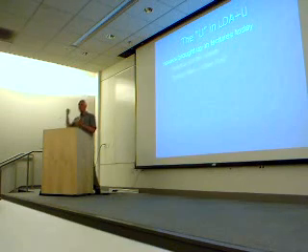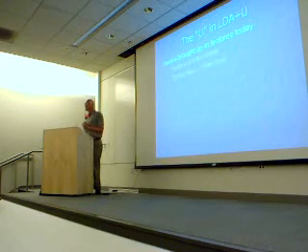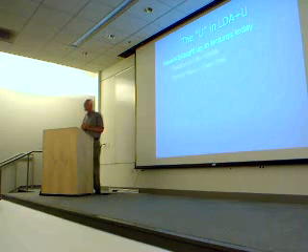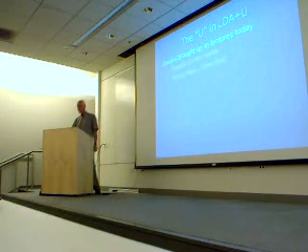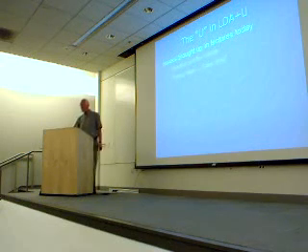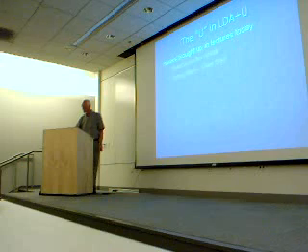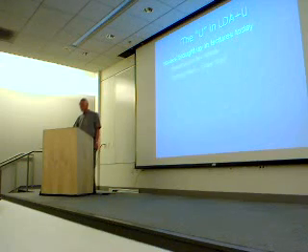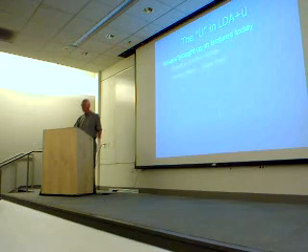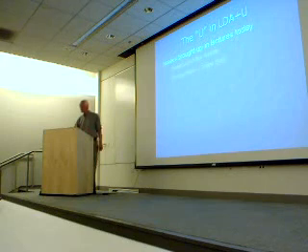And when you put in the U, it's saying it really likes to have an integer value, which is putting in some physics. But you have to identify the interesting states where that actually makes a difference. And in this large set of systems, they're the transition metals or the lanthanides or the actinides that have partially filled D shells. That's what was talked about today.